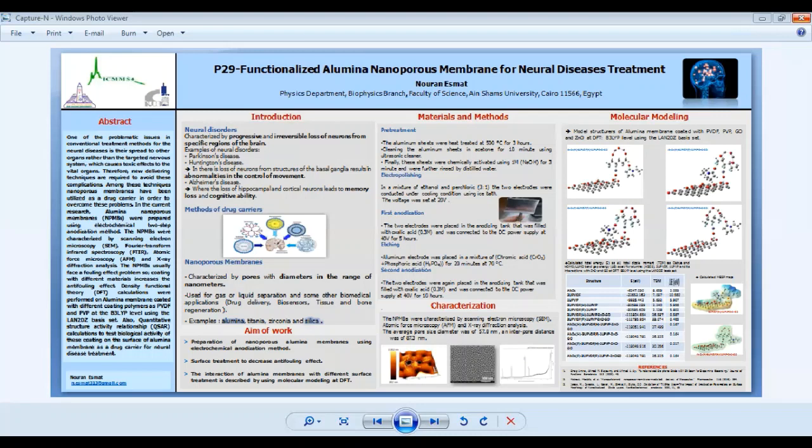Between the two steps of anodization, selective removal of the porous oxide layer obtained by first anodization was done to pre-structure the aluminium surface. This etching process is done using a mixture of chromic acid and phosphoric acid at 70 degrees. The resulting inner surface of aluminium exhibits a uniform concave nanoarray based on which an ordered pore size distribution can be built.